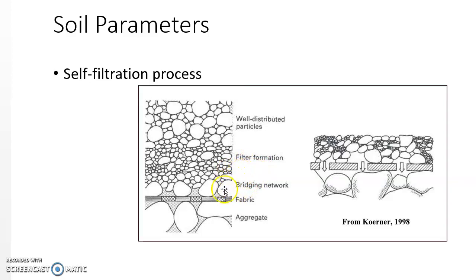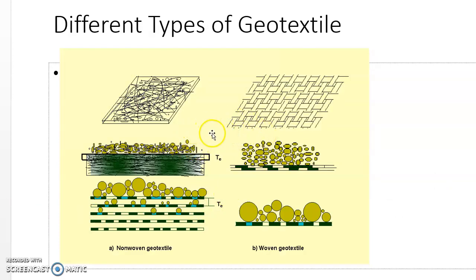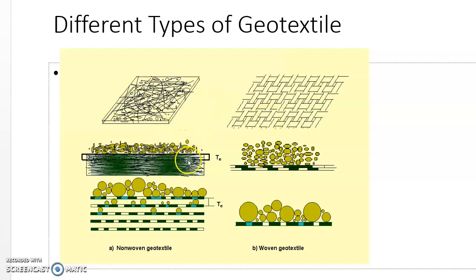This schematic plot compares the woven and non-woven geotextile structure. The woven geotextile has very limited internal space, so it does not allow any capture space for fine particles. But the non-woven geotextile, especially needle-punch geotextile, has room to retain some fine particles inside the geotextile. That is the big difference between woven and non-woven geotextile, and that is why non-woven geotextile is more frequently used as filter media, especially for fine particle soils and tailing material.